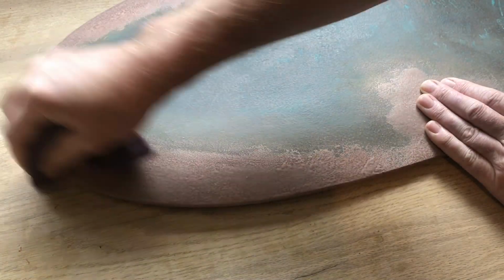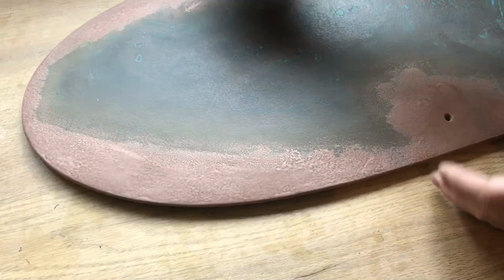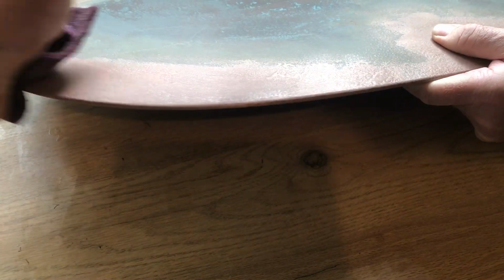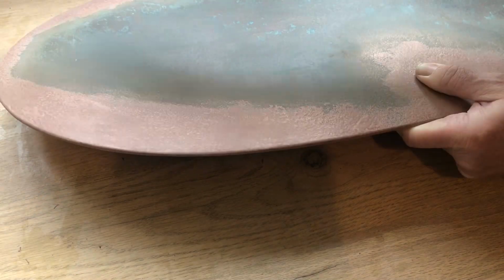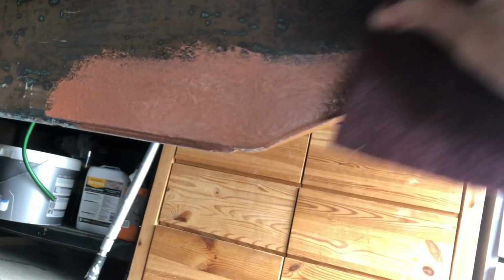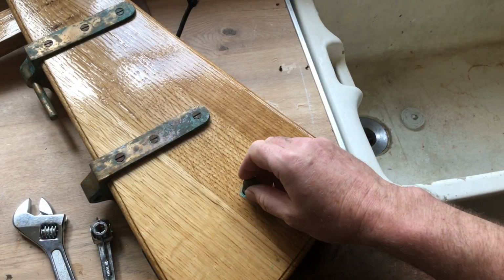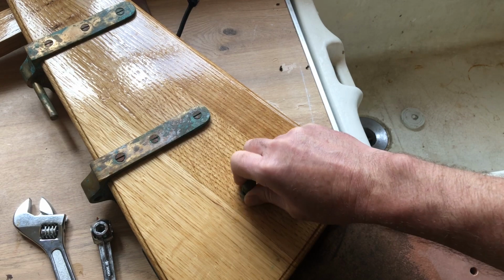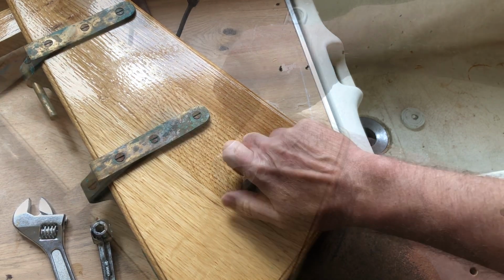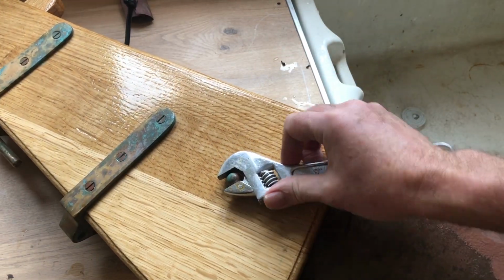Coppercoat recommend using a 400 to 600 grade sandpaper or a fine Scotch-Brite pad. I prefer the Scotch-Brite pad because it gets in between the stipples on the surface of the resin caused by the roller. Coppercoat is a low-leeching, water-based, solvent-free antifoul system that is considerably kinder to the environment than conventional self-eroding antifouls. It can easily last from 10 to 20 years with little maintenance, depending on the geographical region it's used in.